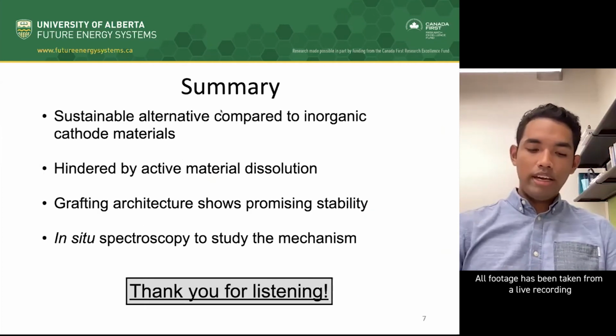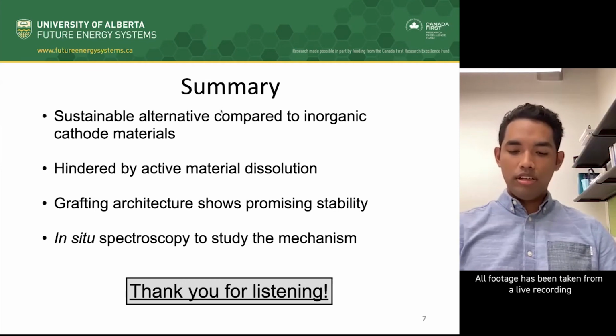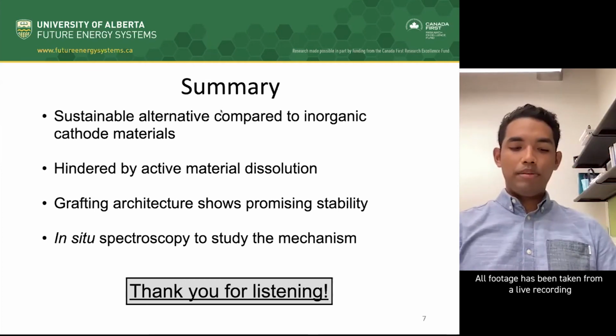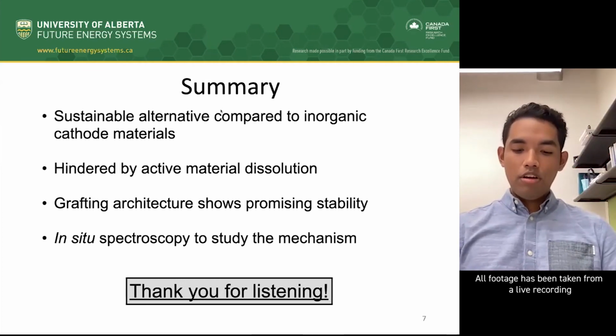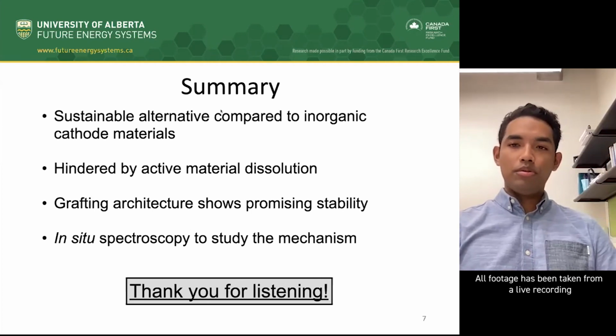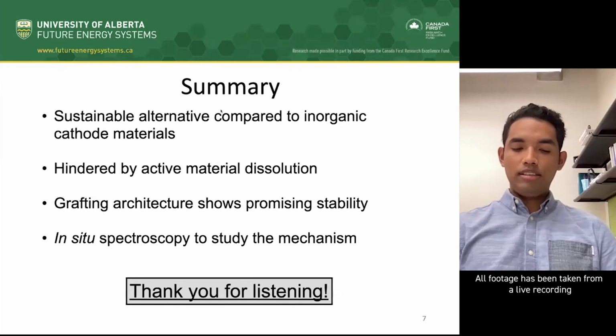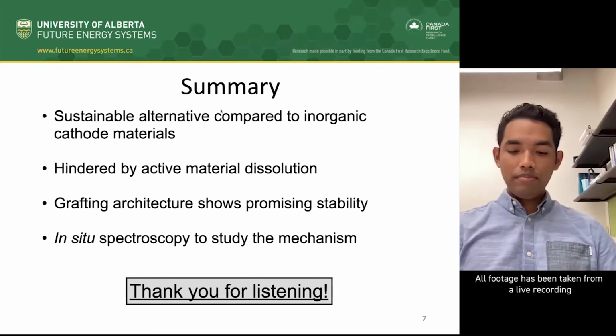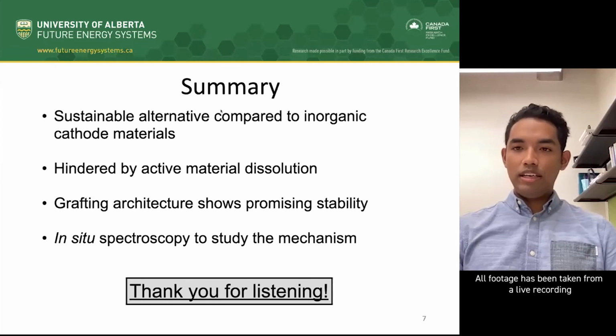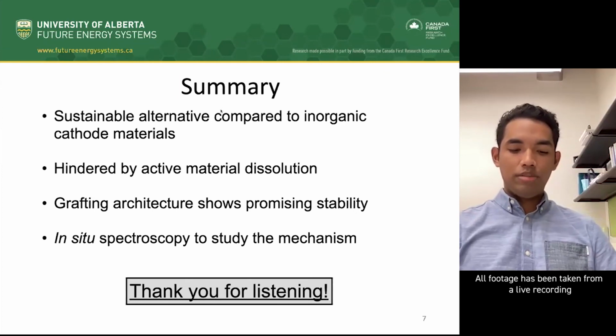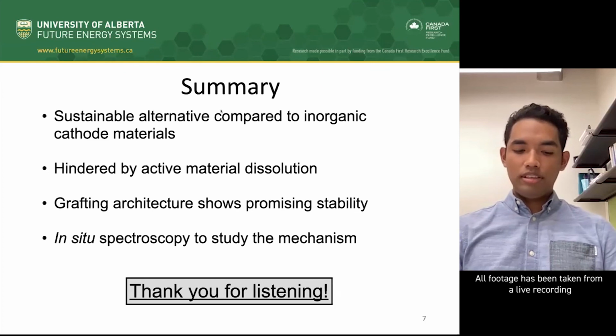In summary, organic cathodes offer a sustainable alternative to current materials by replacing the need for transition metals. Although these organic cathodes are hindered by active material dissolution, we propose that a grafted architecture will stabilize the cathodes and reduce capacity fade. Additionally, development of an in-situ methodology will enable investigation of the lithiation and delithiation mechanism, providing a deeper understanding of these cathodes.